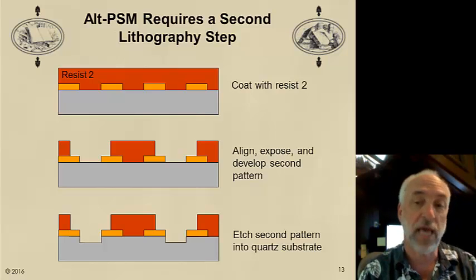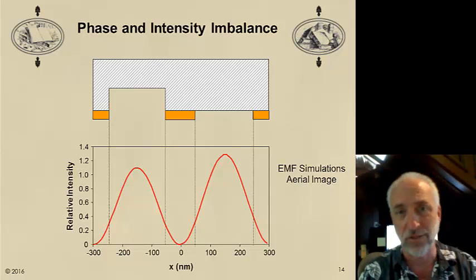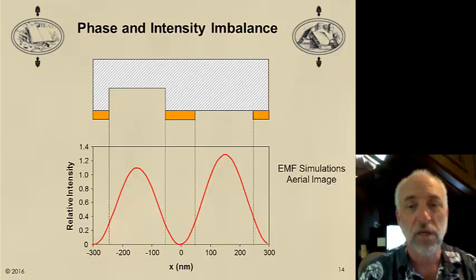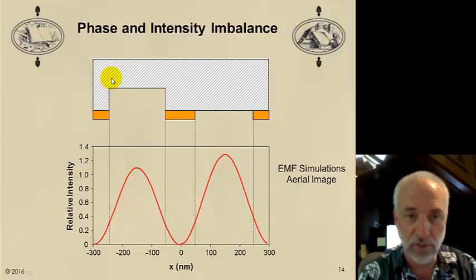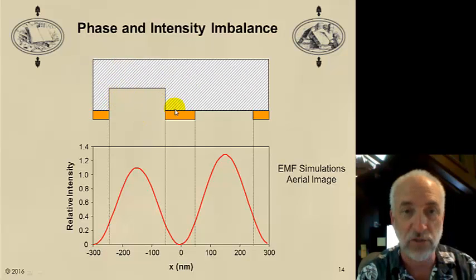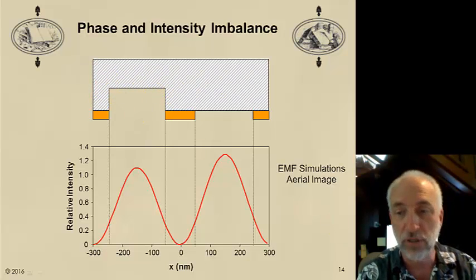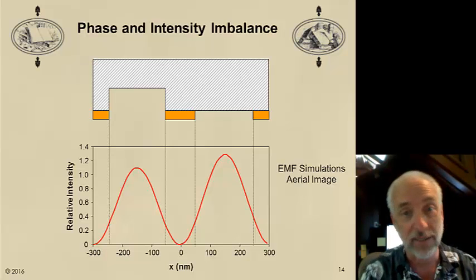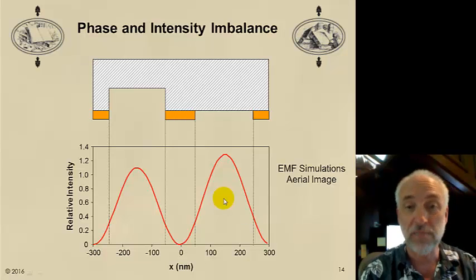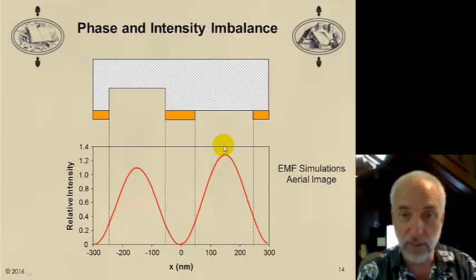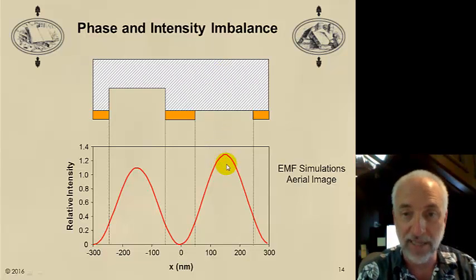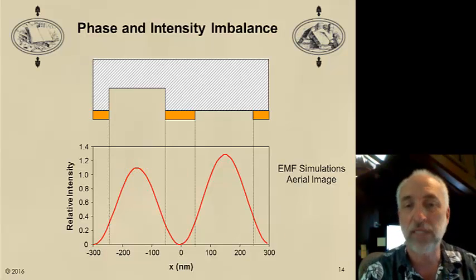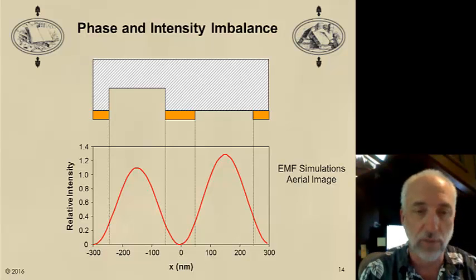Well, we strip the resist here and we have our phase shifting mask, but there's a few extra complications. Something called phase and intensity imbalance. As we've etched this quartz out to make our phase shifters, the way light transmits through this etched out region is different than if I don't have an etched out region. In fact, these little corners of the etched region diffract light, and some of that diffracted light gets absorbed by the chrome, and as a result, the light transmitted through the etched region is less than the light transmitted through the unetched region. If I look at the aerial images that hit the wafer, you see it's brighter in the unetched space compared to the etched or phase shifted space. This intensity imbalance causes alignment errors and various other problems, so we need to fix that.